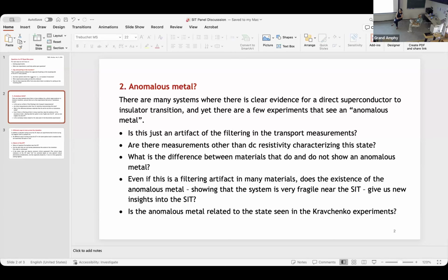So when you say anomalous metal, what is the phenomenological description? So R goes to a finite value in the limit T goes to 0. But before that, it has a drop. Is that drop essential or not? So either it has a drop in the resistance, or it saturates. It's sort of weakly localized and then saturates, and it goes continuously from one behavior to the other. So you have superconducting, then you have a sort of superconducting thing that saturates at finite value, and then progressively it increases. You have weak localization and then saturation, and then you have an insulating regime that is first completely activated and then fermionic. So that's what I call metallic. Whether the dropping one and the weakly localized one are the same phase or not, whether it's still really a phase, I don't know.